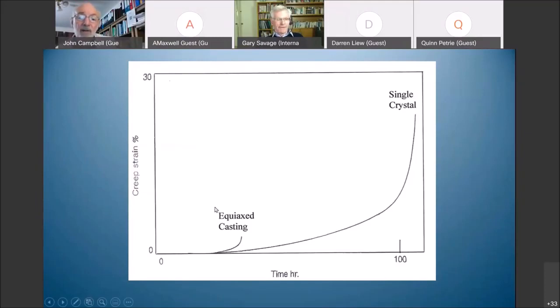So if we look at our standard equiax casting, a normal casting with normal grains growing randomly, and we just pour it in a standard turbulent manner, so we create bifilms, and now we grow grains in amongst the bifilms and the grains expand as they grow. And as the grains move, they push the bifilms ahead. And finally, of course, the bifilms become trapped between opposing grains. And so the bifilms finish at grain boundaries automatically. And so this equiax casting would have bifilms at practically all of its grain boundaries, all over the place.